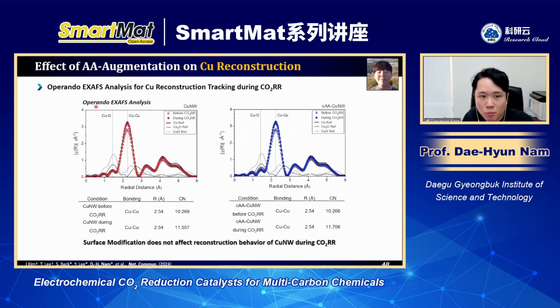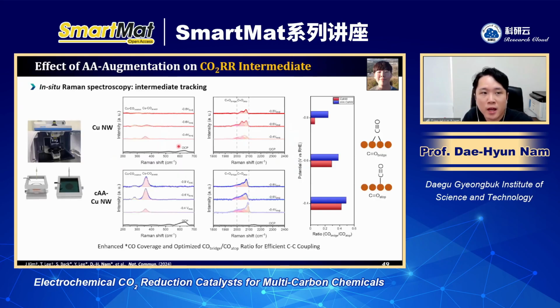And when we measured the operando XAS, we found there is no big difference in the copper active sites. It means that ascorbic acid can work independently as a CO2 capture agent on the surface of the heterogeneous catalyst. And when we measured the in situ Raman, compared to the bare copper, in the case of the ascorbic acid based copper nanowire, we found a lot more CO coverage compared to the bare one. So it means that this ascorbic acid promoted the CO2 to CO conversion. And this also had the effect of controlling the CO bridge and atop ratio. And these also promoted the production of ethylene in this way.